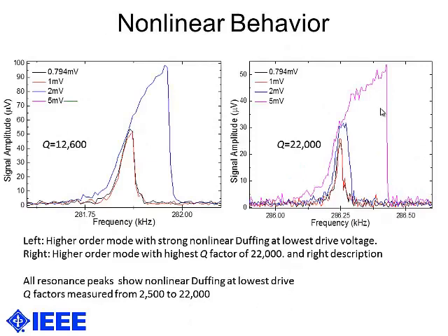We also observed more closely each one of the peaks. Shown here on the left is one of the higher order modes with a strong Duffing. You can see that as the input drive amplitude goes up, you get a strong nonlinear behavior. In all of the peaks that we observed, even at the lowest drive, you can see that there is a nonlinear aspect to these membranes.